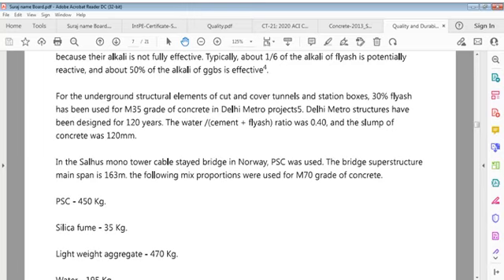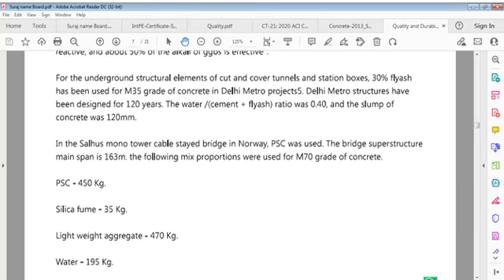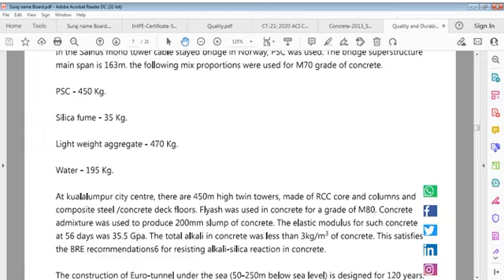In Salux mono tower cable stayed bridge in Norway, PSC was used in the bridge superstructure. Main span is 163 meter. Following mix proportions were used for 70 grade of concrete. PSC 450 kg, silica fume 35 kg. So less than 10%, you can say, this is about, I think, 8%. Lightweight aggregate 470 kg, and water 195 kg.